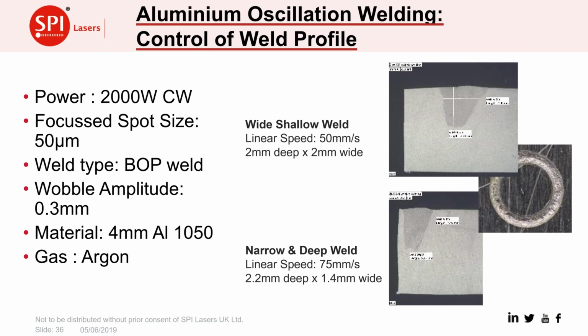And just to look at what we were able to do here, with a relatively small change in speed, we've gone from 50 to 75 millimeters a second. We've kept all the other parameters the same for these welds with a 2 kilowatt laser. As we've been welding around that circular profile, you can see there, we did some cross sections to check what had happened. As we changed the linear speed, we've got a different width to the weld, but also slightly different depth. So this is what we were saying: by changing the parameters, we can control the profile of the weld without needing to change the laser parameters. That gives us another added dimension if we want to get into it.